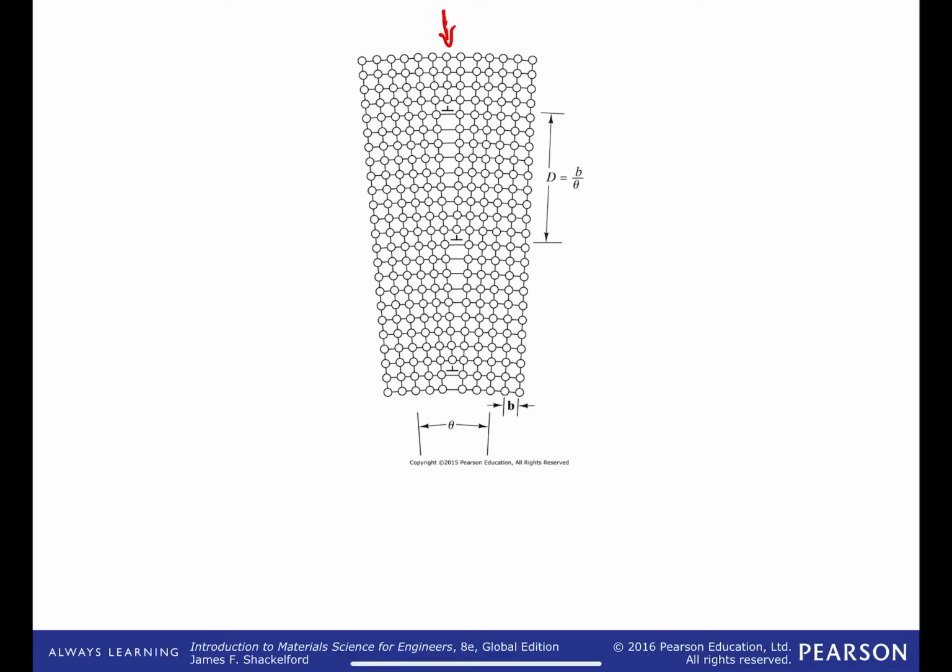So you can see here our edge dislocations, which again we've represented with the perpendicular symbol that we've seen, and a Burgers vector that we know how to determine that is characteristic of this edge dislocation. And we have a nice equation here for determining the average distance between those edge dislocation sites, where that one-dimensional defect coming out of the page at that perpendicular symbol exists.